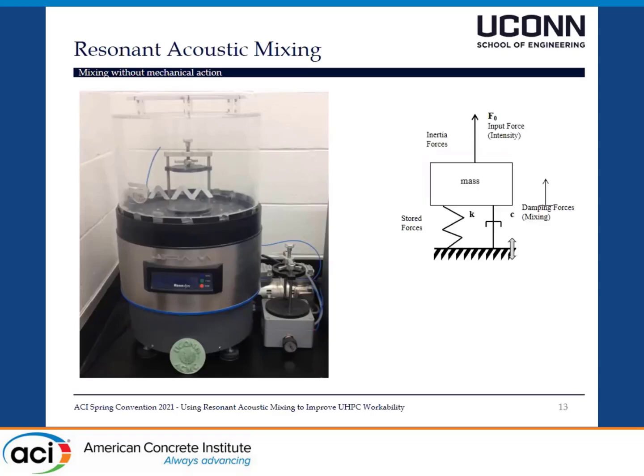And why is it called resonant acoustic mixing? It's because the stored forces in the springs are meant to cancel out the inertial forces from the mass right here. And it's acoustic because the frequency of the pressure wave is set around an acoustic frequency of around 60 hertz. Though the exact frequency can be varied depending on the vessel mass, the fill level, the compressibility of the material, if the material couples to the vessel walls, what the material density is, the vessel geometry, what the vessel internal pressure is, and what type of mixing regime you follow.